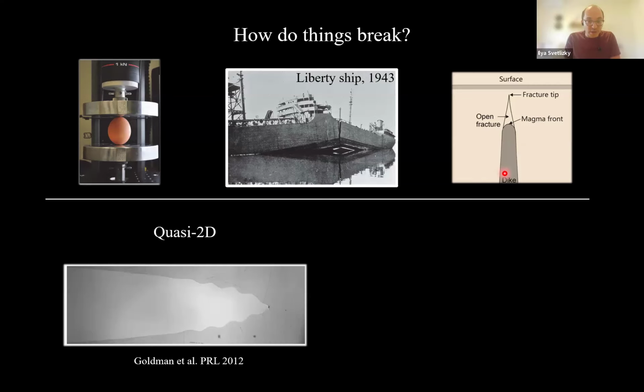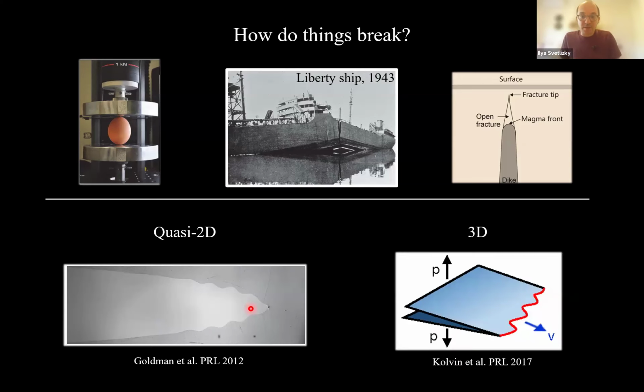Now, people have addressed fracture mechanics or cracks for a very long time. And let me define that the crack tip in quasi-2D samples is a point. The point separates the intact material on the right from the broken one on the left. And in 3D, the crack front is no longer a point, it's a line. And what makes the 3D fracture interesting is that the crack front can curve. It can curve in and out of plane. And it induces a lot of challenges, both from a theoretical perspective and from an experimental perspective.